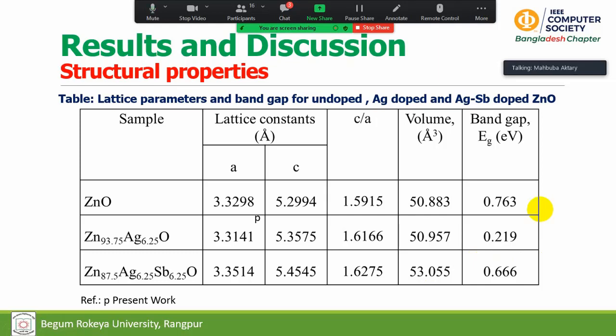And here you can see some band gap values calculated by our computational method based on CASTEP code. And there the value of band gap has been first lowered by silver doping, and after then if we implemented antimony with silver on zinc site, then we can find a larger band gap value.